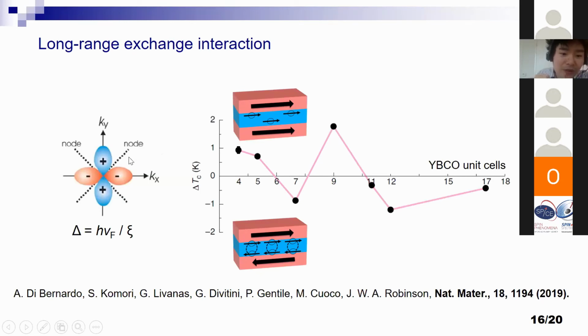And D-wave pairing symmetry has a nodal region where the gap is very small and coherence length is, how to say, effectively very long. And we are thinking pairs and quasi-particle excitations around these nodal regions are playing an important role in this long-range exchange interaction. And details are basically discussed in this paper.